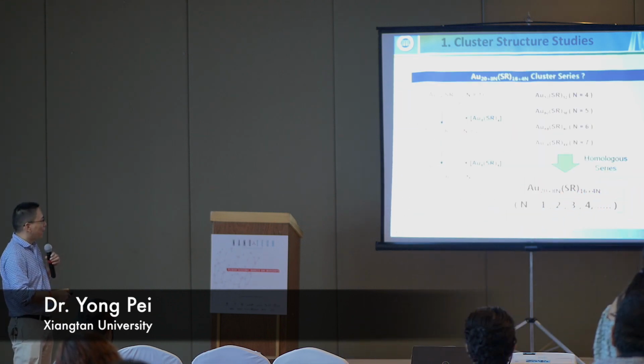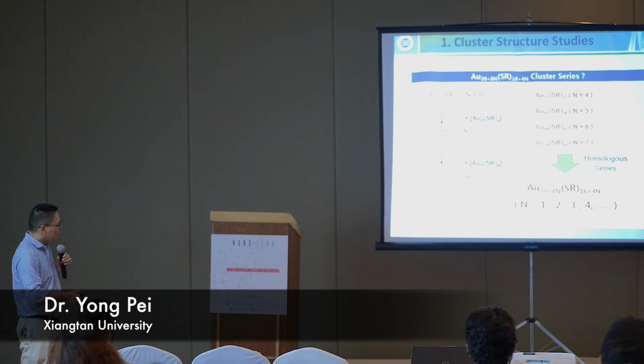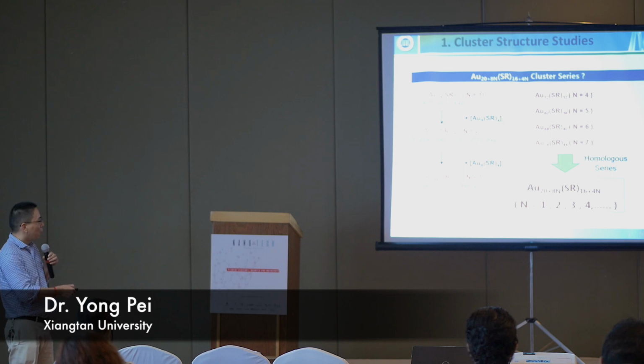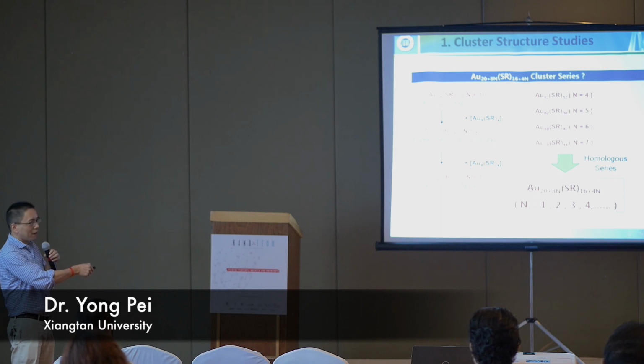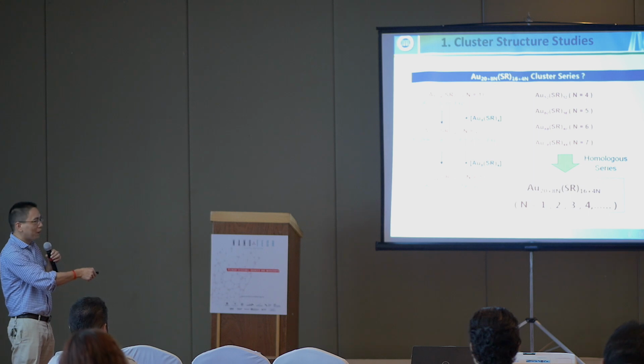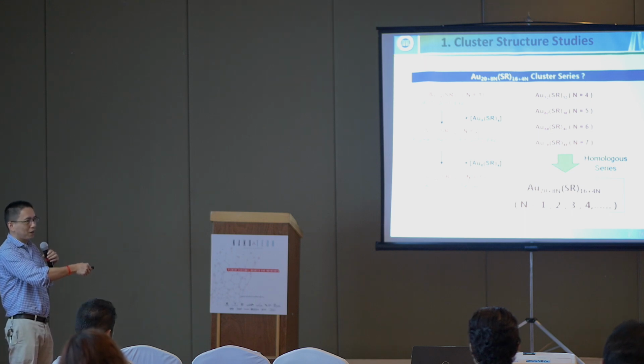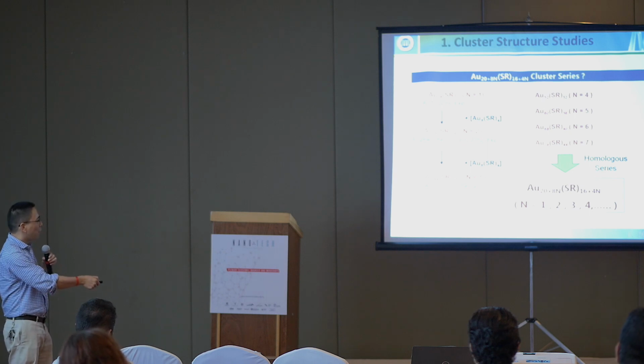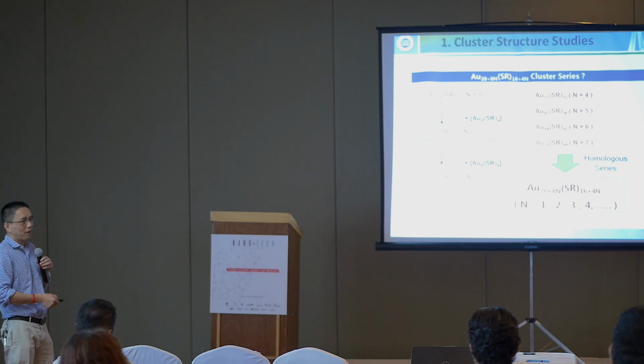Another thing we find from this cluster structure is that the structure we predicted for Au44 has a very good relationship to two previously reported clusters, for example, Au28 and Au36. You can see, from Au28, when we add Au8(SR)4, we reach Au36. And then we add another unit, the same unit, we go to Au44. If we continue to add this unit, we will go to a series of clusters. This is a homologous cluster series. And it has a general formula here, with n being 1, 2, 3, 4, 5, and so on.